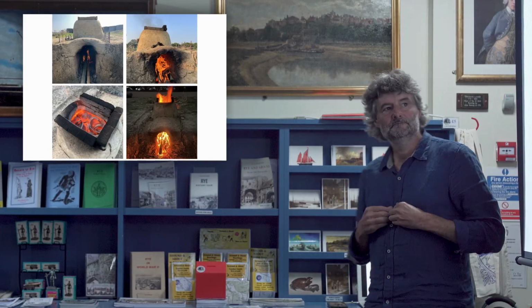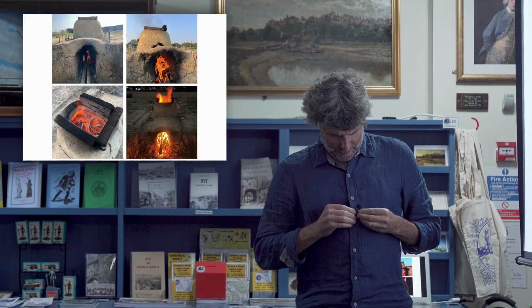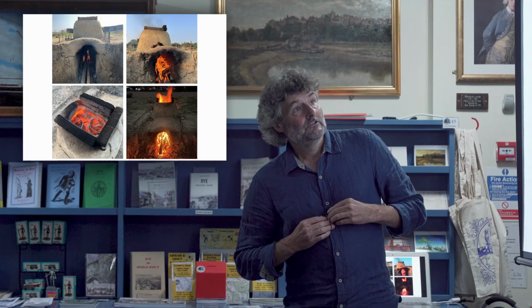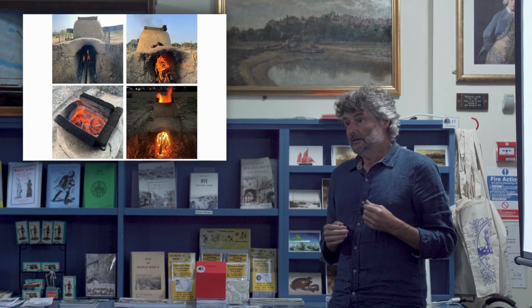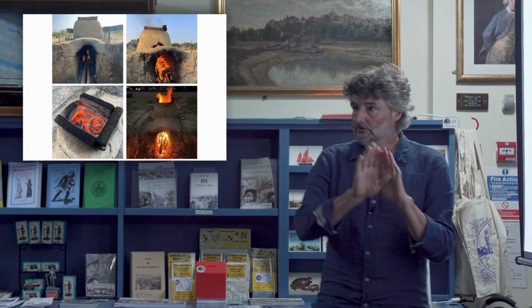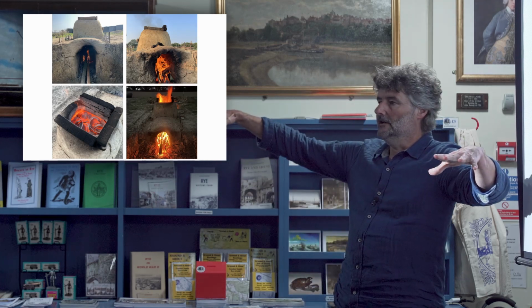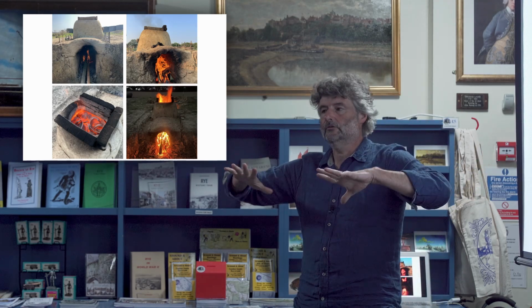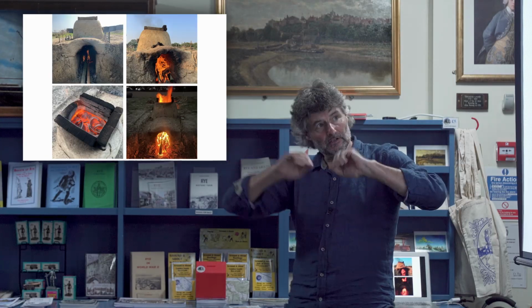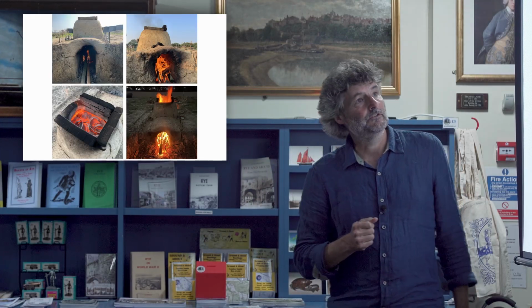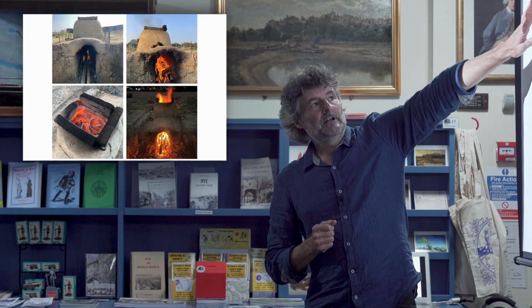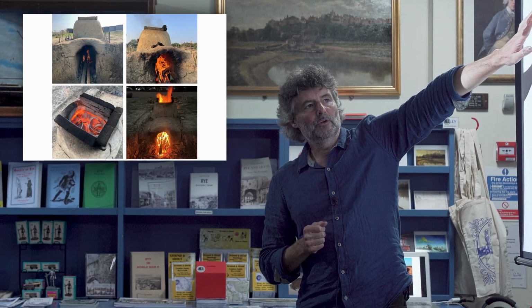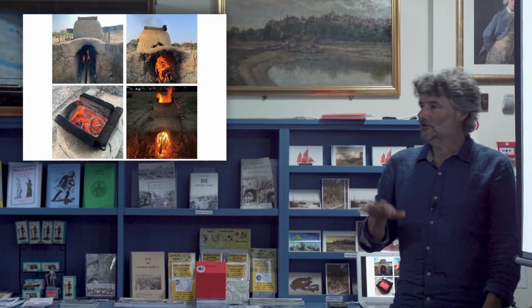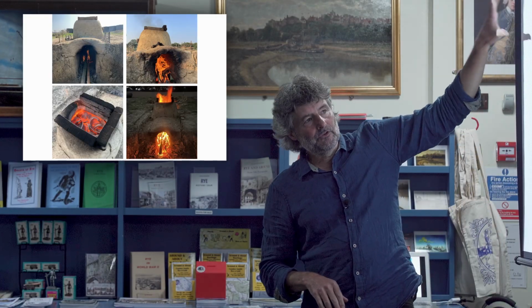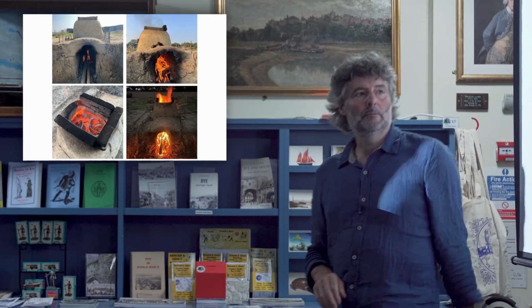So then comes the bit that everyone is interested in, which is the hot bit. So it took us 14 hours to fire the kiln. Partly that's because you need a very long, slow initial phase to drive all the water out of the pots, because when water turns to steam in the clay, that is when a lot of breakage occurs. So we ran the kiln with quite small fires to begin with. It's really difficult actually to keep the kiln under 100 degrees. It's really, really fiddly.